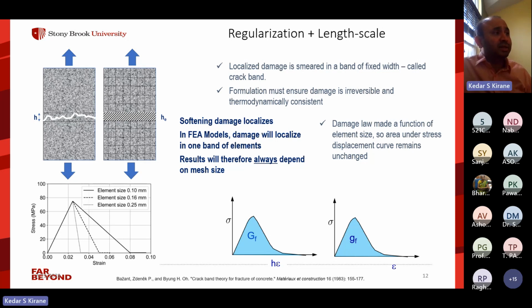Now, I do want to say that this is a different length scale than the D0 from the size effect law that I mentioned earlier. The D0 from the size effect law is related to the length of the fracture process zone, whereas this h is the width of the process zone, and the width needs to be incorporated in the models to get rid of the mesh dependence issue.